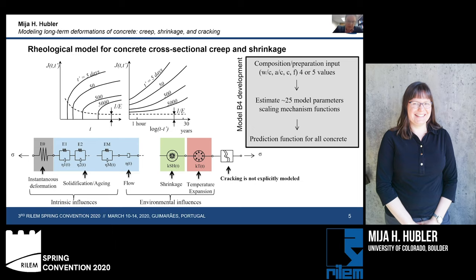To model this type of compliance behavior, we can use a sequence of rheological components to capture the instantaneous deformation, the solidification and aging, the flow of the material, as well as the environmentally impacted shrinkage and thermal expansion. One thing that is not explicitly captured in most models these days is, in fact, the cracking of the material.